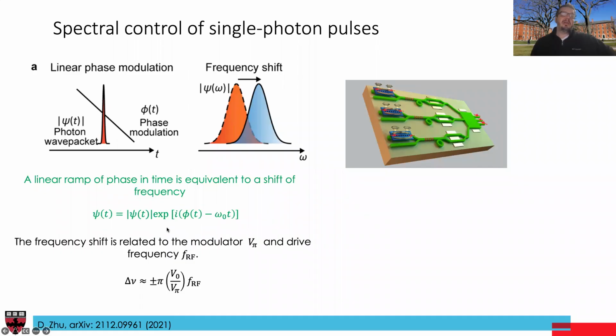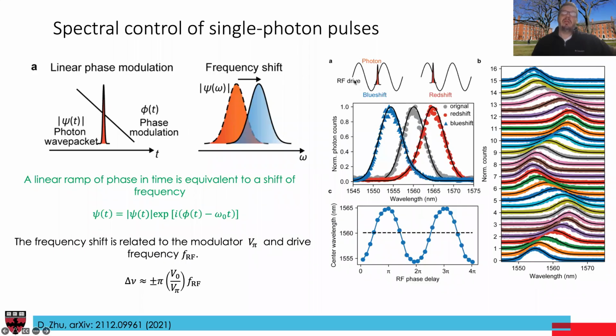If I have an electromagnetic wave where the phase can be modulated in time linearly, that is basically equivalent to adding a frequency shift. This is called spectral shearing. The way we do this is we take a phase modulator, apply an RF drive, and then time our optical pulses to be synchronized with the rising edge of a simple harmonic RF drive, in which case we get a frequency upshift, or if it's synchronized with a trailing edge, we get a frequency downshift. And we showed that using this on single photon pulses, we can actually move the comb by about plus minus 600 gigahertz. So we generate a comb at, let's say, 1550, and we can move it plus minus 600 gigahertz.